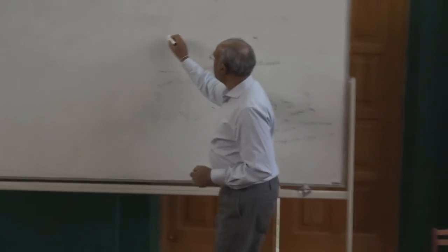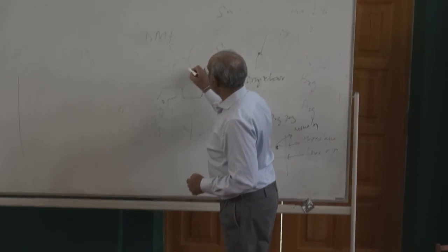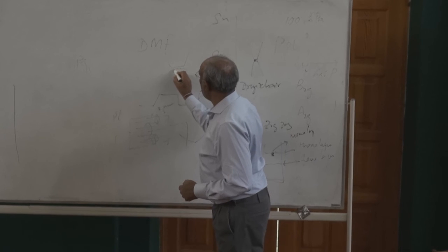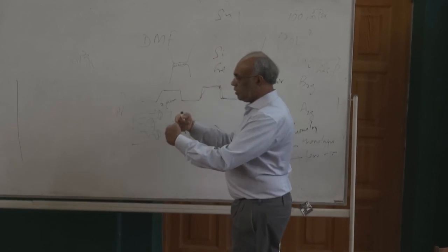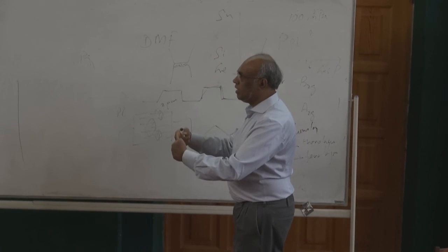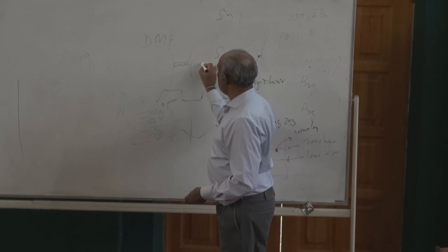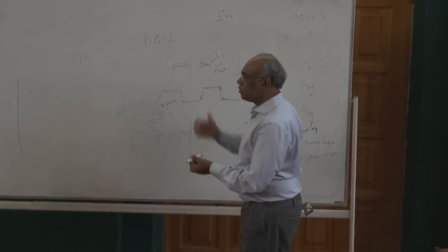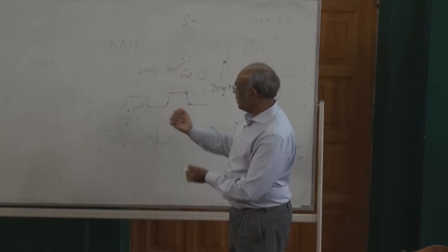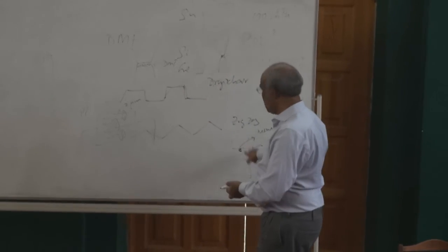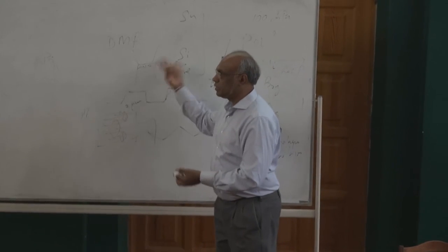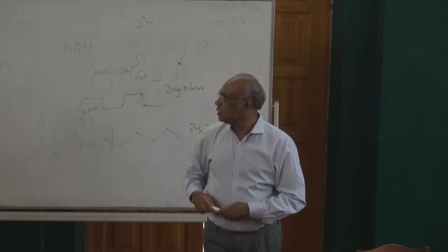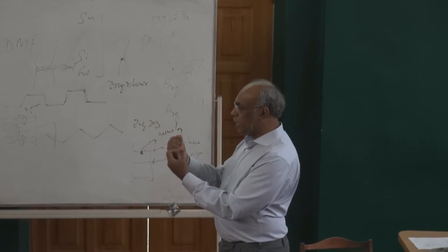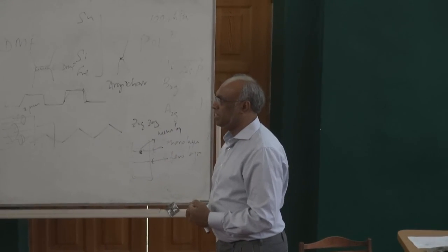We need to have the liquid because when you use this diamond anvil cell, you need some kind of liquid as a pressure transmitting medium. So that's why we use the same DMF. That's a nice thing: you take it from the liquid here, then put it here, and then you have that medium also. Like Victor said, if you don't have a medium, you will just crush the sample.